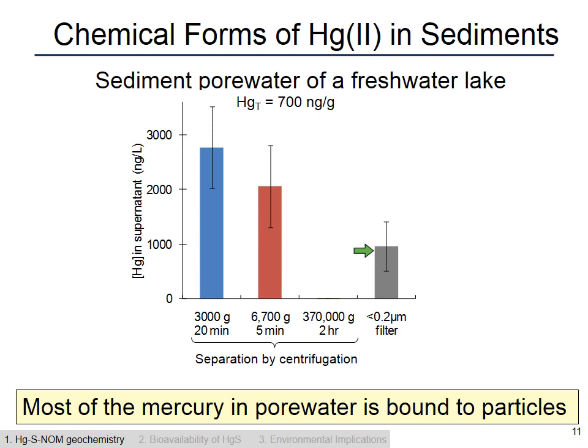You can try to do other methods of separation, for example, centrifugation, which is what we've done here. What I'm showing here is the concentration of mercury in the supernatant of this sample for three different centrifugation speeds to separate particles from water. The key thing here is that when you apply ultracentrifugation, which removes particles that are on the order of 5 nanometers in diameter or greater, we basically remove all of the mercury from that water and fall below our detection limits for mercury in the water.